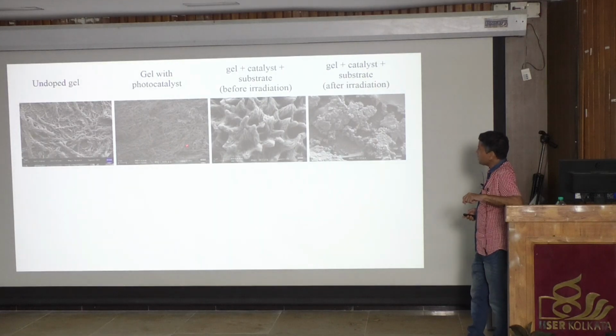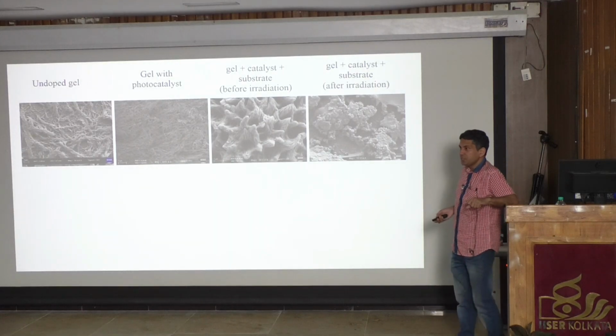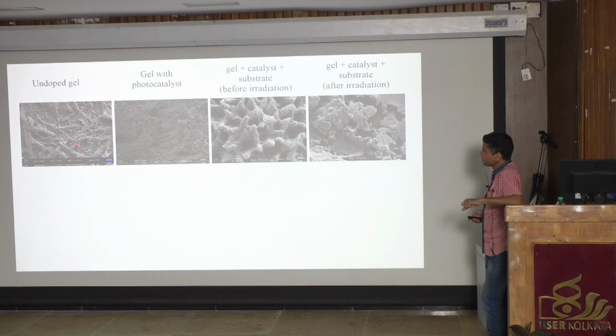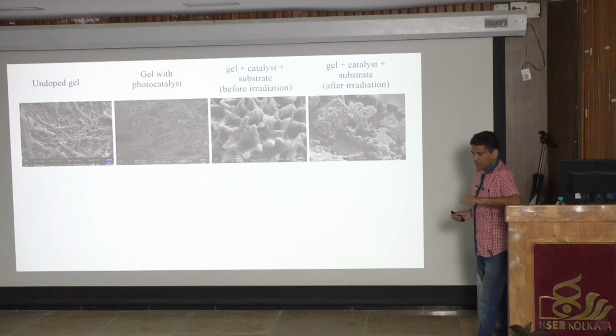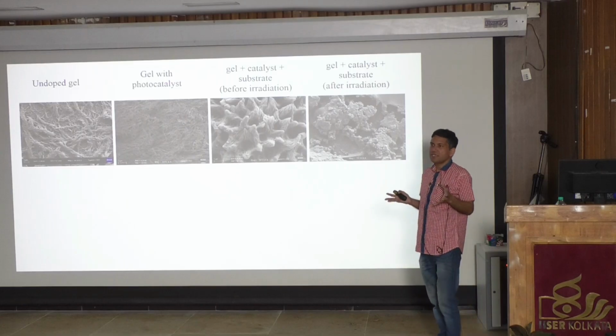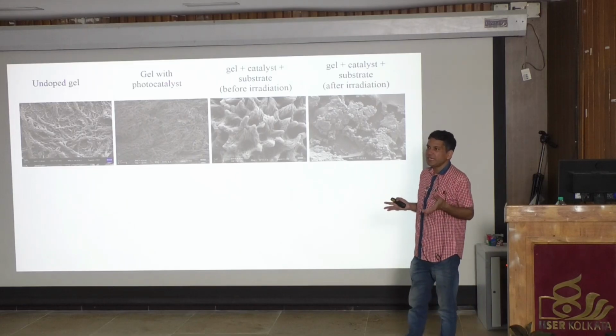And then we studied the morphology of the gel before and after reaction. So this is the undoped gel, that is only gelator. And then with the photocatalyst and the substrate, the gel looks like that. After light irradiation, when the gel melted, it looks like that. That means once the gel melted, our reagents are exposed to the air, and by that time oxygen is killing the reaction. And so we are stopping at 68% product.